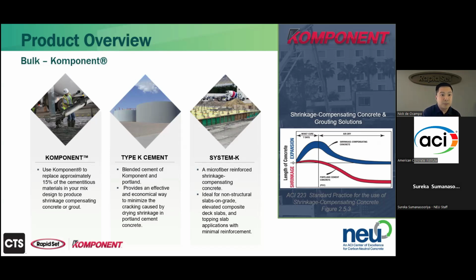A typical replacement for Komponent into Portland cement is around 15%, but if the Portland cement has low shrinkage, that can be as low as 10 to 15%. And if it is high shrinkage material for whatever reason, we can dose that higher for additional expansion to compensate for the added shrinkage that's expected. Type K is a pre-blended version of this, and System K is Type K with microfibers added for additional restraint.